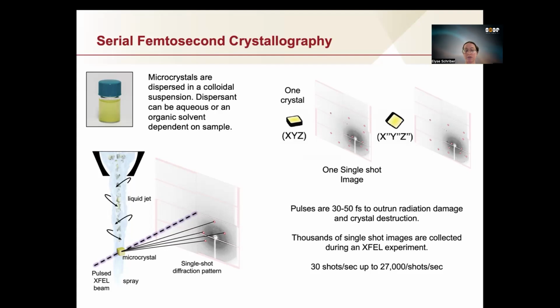But these are all microcrystals, and if you were to take a projection of all the thousands of images that you get in an XFEL SFX experiment, it would start to look very similar to that of powder diffraction. So thousands of single shot images are collected during an XFEL experiment for the same reason why you repeat a measurement during single crystal diffraction, because you want to be able to improve the fidelity of the measurement you're taking.